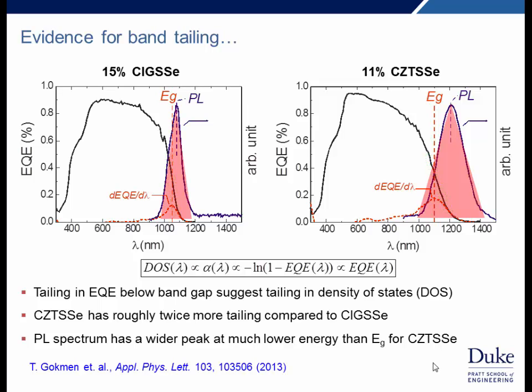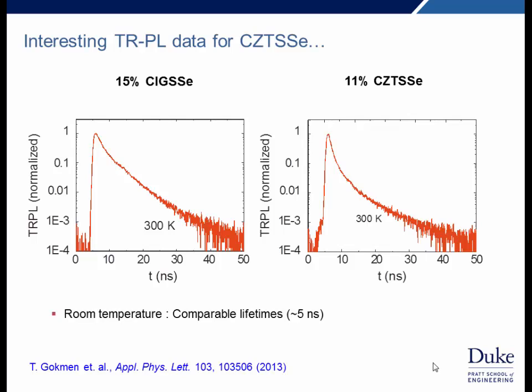Likewise, photoluminescence, the PL peak is broader and shifted further from the band gap value in CZTS compared to CIGS, and this is also indicative of band tailing in the material. From time-resolved photoluminescence, comparing CIGS and CZTS, the lifetimes are fairly comparable, around 5 nanoseconds at room temperature.